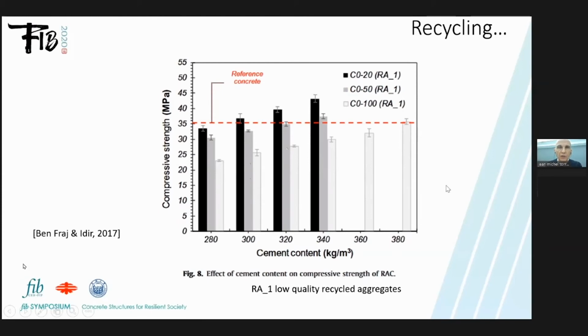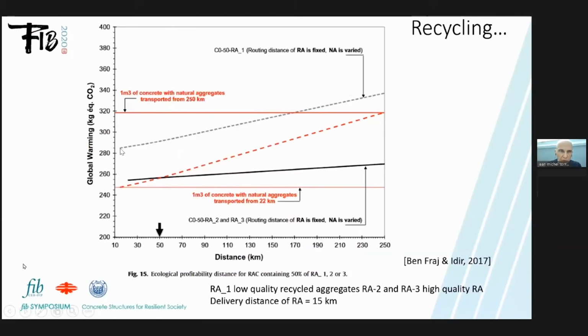Of course, it's different when you have better aggregates. So the curve here corresponds to the concrete with the low quality aggregates. This curve, here in black, corresponds to high quality aggregates. And here you have the CO2 impact of 1 cubic meter of concrete with a natural aggregate transported from 22 kilometers. And here transported to 250 kilometers. And this line is going from this level to the other one with the impact of transportation. So in red, it's for natural aggregates, and the black lines are for recycled aggregates.